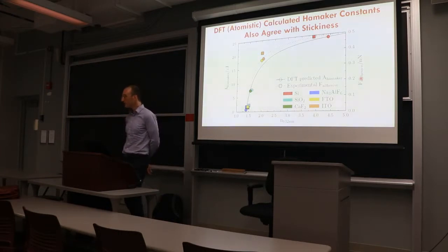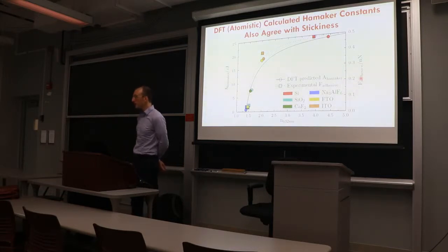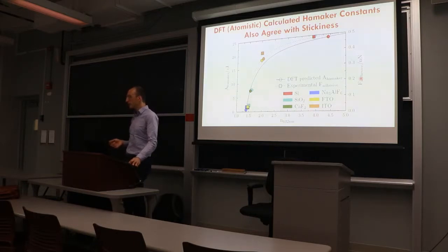How do you characterize the film on the material? Does the film stick really well to the cladding? The film adheres really well as long as it's thin enough. How do you know? We can try scratch tests and fretting tests. We're actually buying a fretting machine to make sure that, when you slide the coating into the spacer grid, that spacer grid, when it sits there gripping the cladding, vibrating about, you don't cause early fretting.